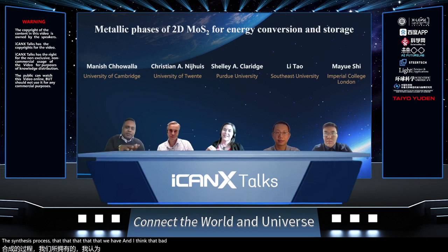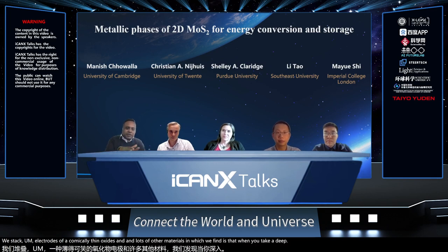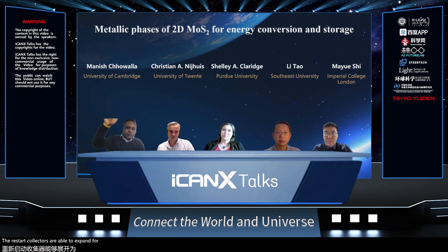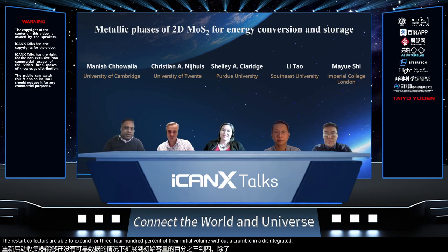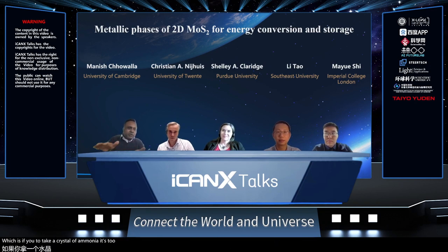and I think what is interesting about these restacked electrodes is that, for example, in Japan there's a group that has been looking at restacked electrodes of atomically thin oxides and lots of other materials. And what they find is that when you intercalate these things, the restacked electrodes are able to expand 400% of their initial volume without disintegrating. Versus if you were to take a crystal of MoS2 and start intercalating different ions, it would disintegrate and crumble into small pieces.